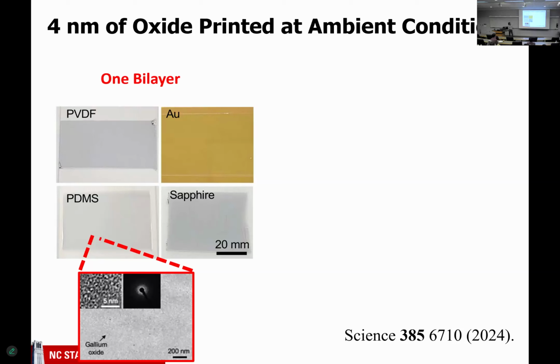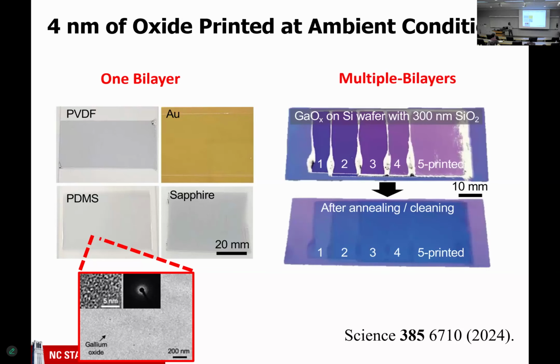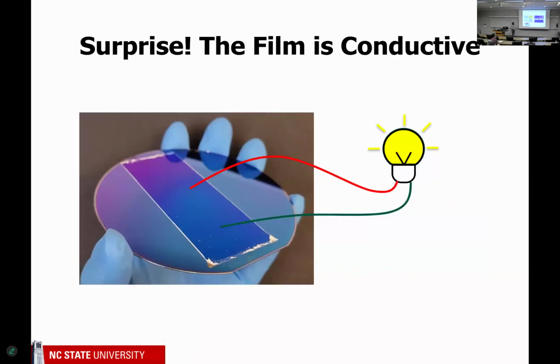The oxide we deposit is amorphous, not surprising. Most native oxides, as far as I know, are amorphous. And even though we only get 4 nanometers with one pass, we can do multiple passes. We can print, print, print. And you can see there's some liquid metal residue, but when we wash that away, you're left with just the oxide. So we can control how thick this is.